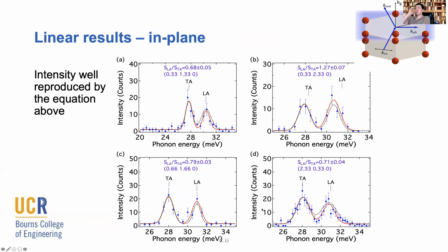So this is what we find when we put the basal plane of the lattice in the scattering plane. Here I'm trying to show what the scattering geometry is. Basically, K in, K out, and the wave vector of the phonon are all in this basal plane, okay? We look at many K and K prime points, and we are plotting our measurement versus the calculation. You can see the dashed line is our calculation.